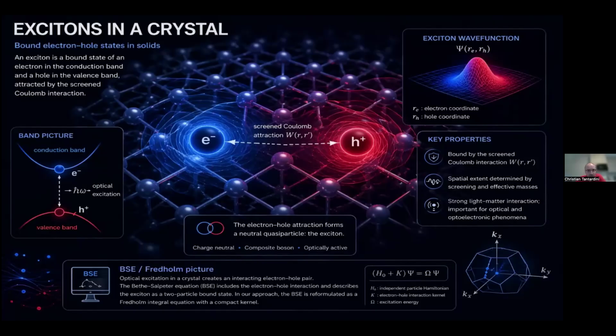So excitons in crystals affect the absorption spectra a lot, because computationally, when we use DFT, we have the self-interaction error that affects the valence band and can be removed using the quasi-particle approximation, GW. But the formation of the exciton, the coupling between hole and electron, is called optical excitation and affects the optical spectra, and it needs to be described by the Bethe-Salpeter equation. Briefly, as a spoiler about what I'm doing, it is to rewrite the Bethe-Salpeter equation using an approximation that changes this problem and makes it more numerically possible to solve, also for big systems.